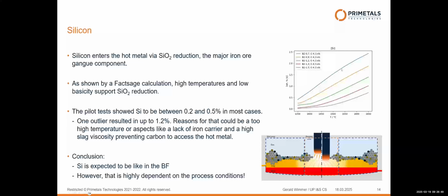And we see it's temperature dependent. The higher the temperature, the higher the silicon. For a temperature of 1450, for example, for the slag and a basicity of 1.1, the equilibrium would be somewhere at 0.4% of silicon. So that's why for the silicon level, we expect that the levels are quite similar to what we see today on the blast furnace.